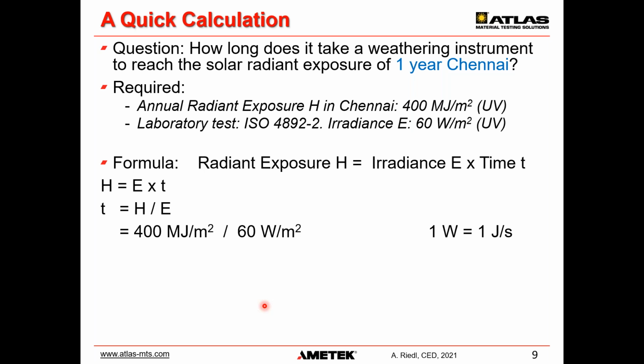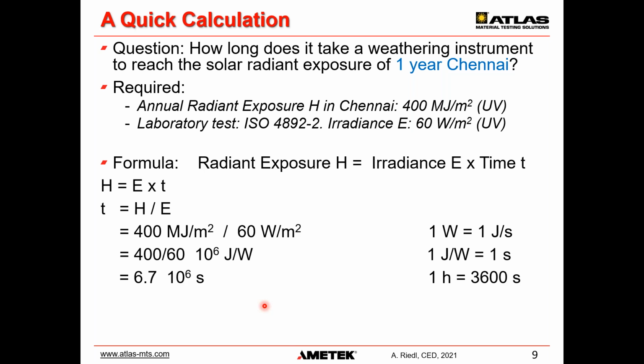I chose the values because they are easy to calculate without a calculator. 400 megajoule per square meter divided by 60 watt per square meter. A watt is a joule per second, so a joule per watt is a second. It's very easy. It's 400 divided by 60, which is 6.7 megaseconds, million seconds, 10 to the 6th, which is 11 weeks. And then the acceleration factor is 52 weeks divided by 11 weeks, because a year in Chennai, and by the way, everywhere else, is 52 weeks. And this leads to the acceleration factor with an index E, meaning irradiance only, of 4.7.